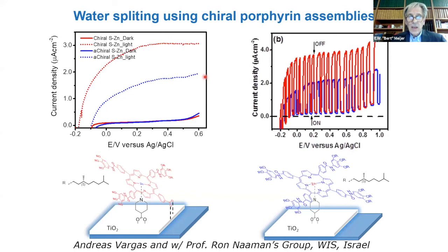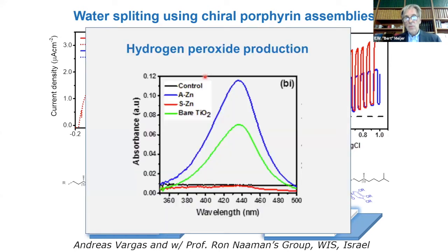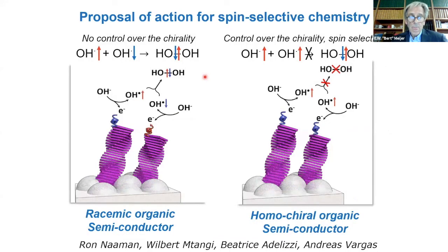But then the breakthrough came by measuring hydrogen peroxide. And hydrogen peroxide seems to be a side product in the water splitting to oxygen and hydrogen. And every time that we use bare titanium dioxide or an achiral structure, what we see is that hydrogen peroxide is formed. Well, if we use the chiral zinc porphyrin or any other structure that we measured in the meantime, it doesn't give you hydrogen peroxide. And there I'm very excited, because that could give you the following cartoon.